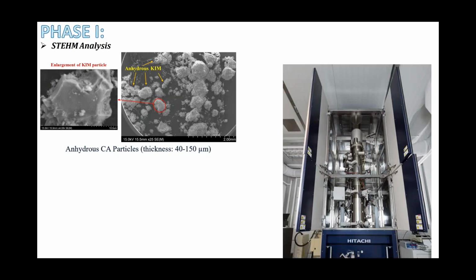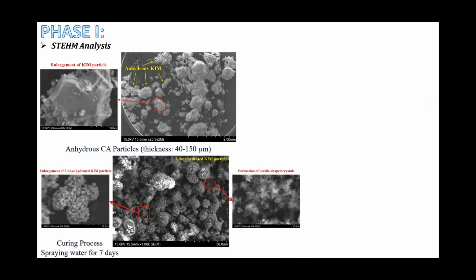And then I sprayed water on top of my samples, on the powder, and I kept doing that for 7 days. As you can realize, the formation of needle-shaped crystals on the right-hand side of the SEM image is obvious. And also all the particles are somehow swelling, and hydration is going on inside those particles.